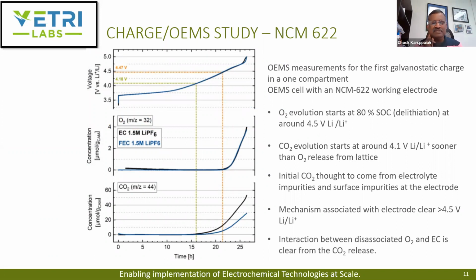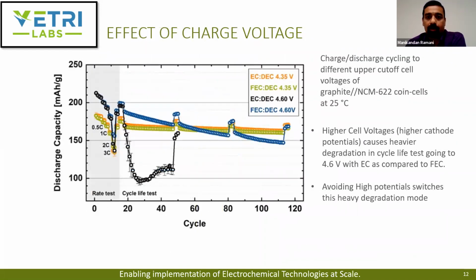If that's the case, my question was if we had actually capped the charging voltage to 4.1, would we have seen a better cycle life? Which they did, they did it at 4.35. But they're still showing at 4.35, it's still better than 4.6 cell voltage.